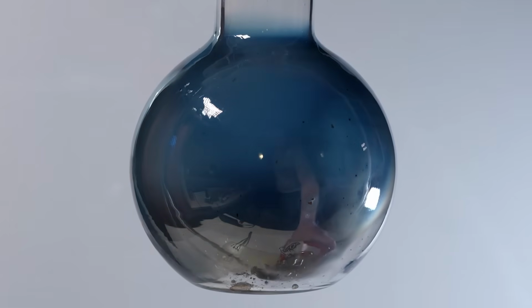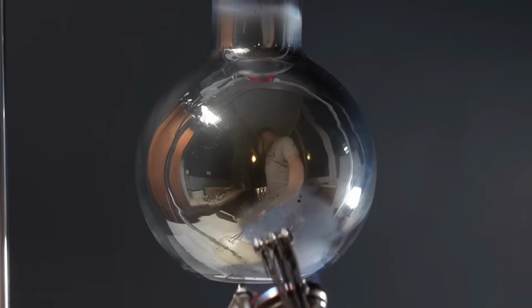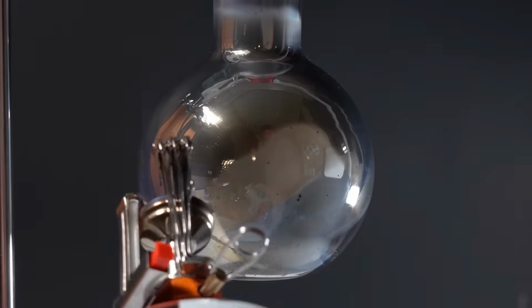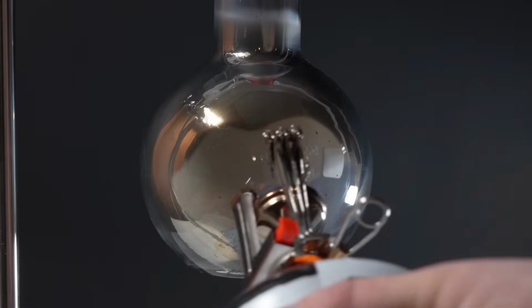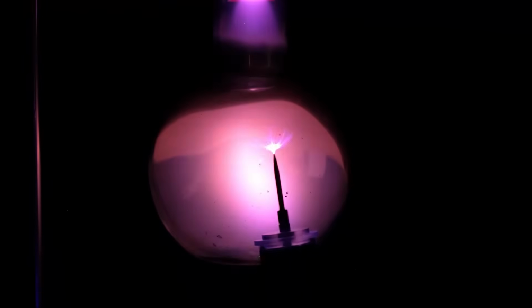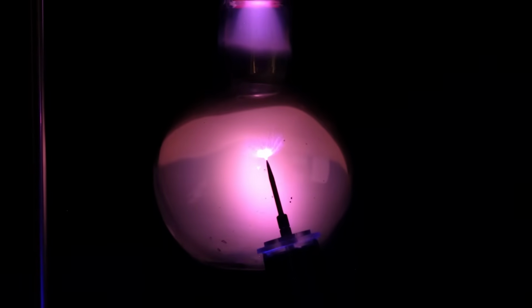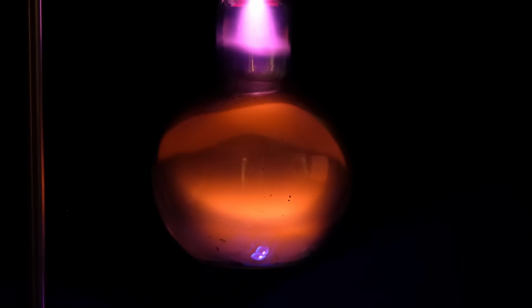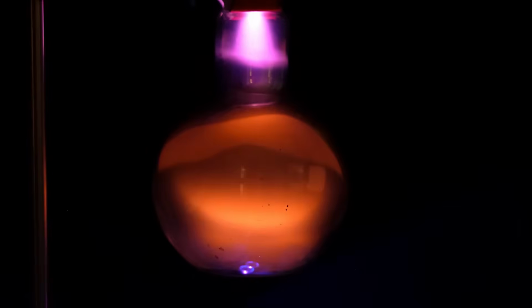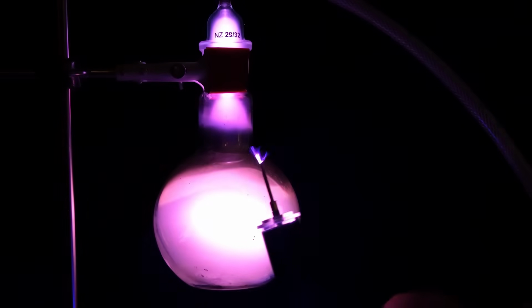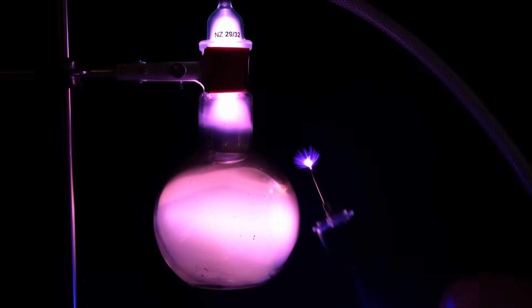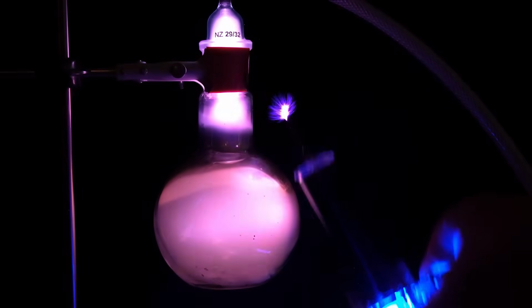Yes, it looks pretty good, almost like with rubidium. But here, the cesium mirror has a subtly golden tint. After heating the flask, I once again create plasma inside it, but this time from cesium. By the way, the color of the plasma here turned out to be quite unusual, because near the Tesla coil, the cesium vapor glowed pink. And as soon as I moved the coil away, the glow became slightly orange. I think this happened because cesium atoms are larger, making them respond differently to electromagnetic radiation of varying intensities.